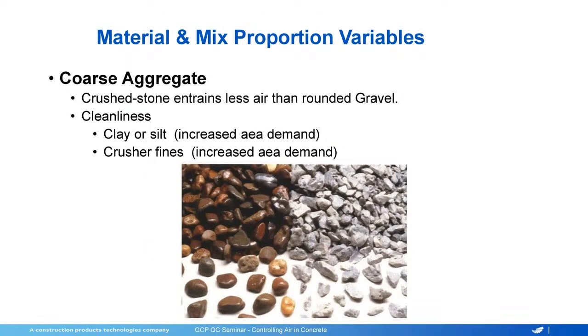So again, consistency in your aggregates and managing your stockpiles is key. If you have a loader operator managing the stockpile, someone that's doing a really good job can make life much easier with getting air than someone that's not. So backstacking your stockpiles, not digging too low in the stockpile, not digging in one spot for the entire day, because then you tend to start segregating the stockpiles.